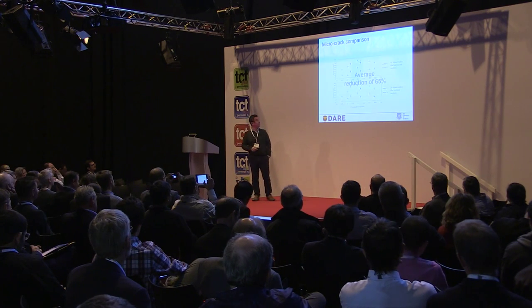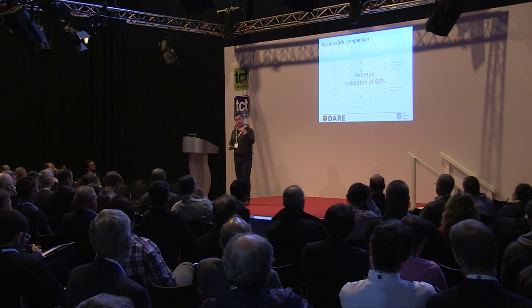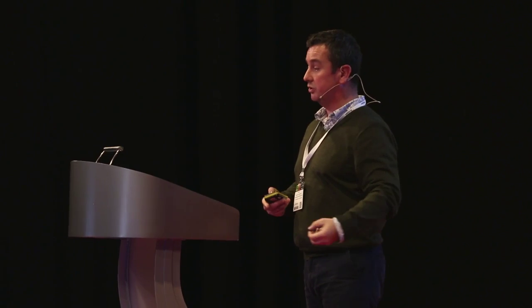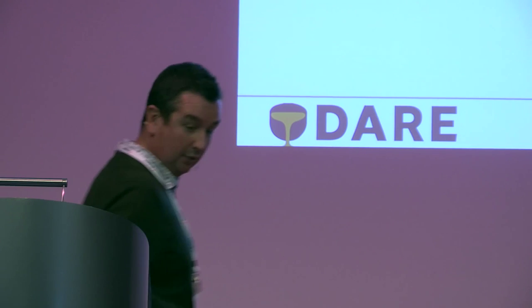The result doesn't get rid of cracks altogether, but it certainly reduces them. We have to remember it's not the only trick — we can also change the bed temperature and reduce the stress. We can start to play tunes with our material, thinking about the interaction of process and material to give a composition suitable for the process. And you can do it without any crazy new alloying strategies — though being a university professor, that is also my job.